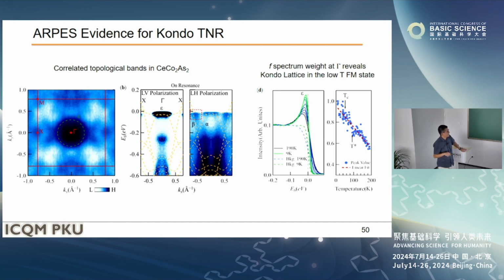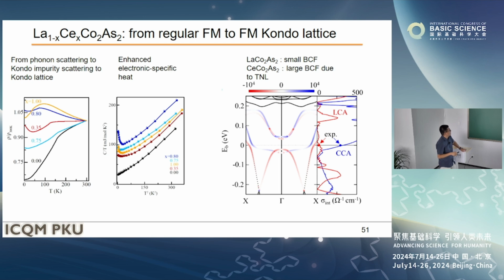This is a measurement at different temperatures. At high temperature and low temperature, you see the 4f electron spectral weight is much enhanced at low temperature. This is a signature of the Kondo effect, because the Kondo effect is a crossover from local moment to itinerant moment down to the lowest temperature. Okay, so we also made this kind of a doping series, increasing the x cerium composition. It starts from a regular ferromagnet, lanthanum 122, to cerium 122.